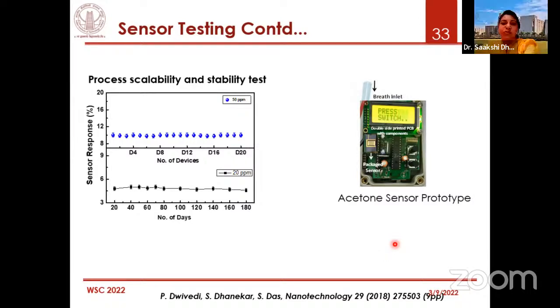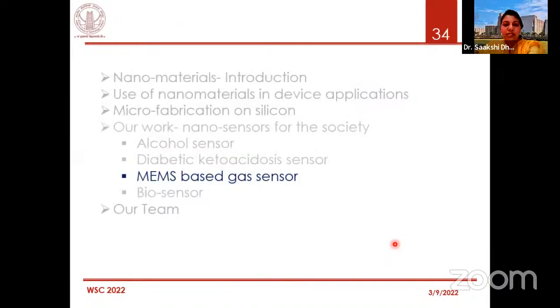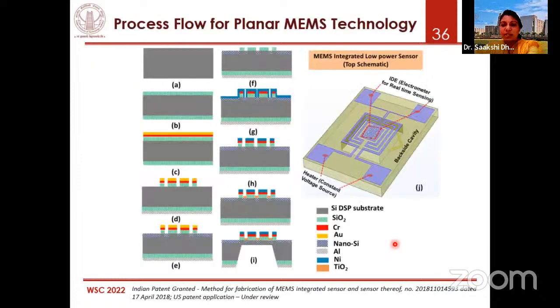10 minutes, okay, thanks. I would also like to discuss some part of this MEMS-based gas sensor, which we found very interesting, mainly because we found that no one has done it before. Nanostructured silicon is formed when you make a pore in a material, etching and making a groove, a V or U shape. Now, if I want to integrate a heater with it, it's extremely challenging because you have to do lithography, backside etching, something like this that you see here, and then various steps to have contact pads also.